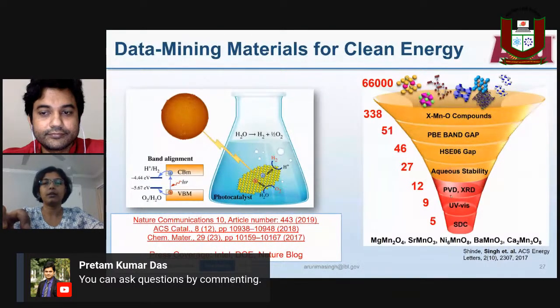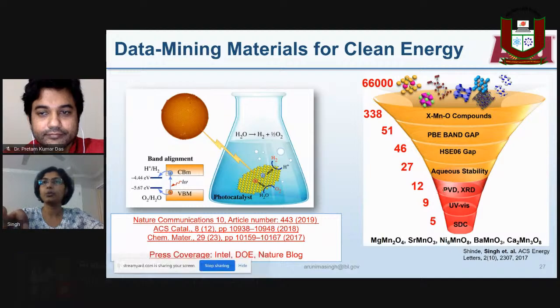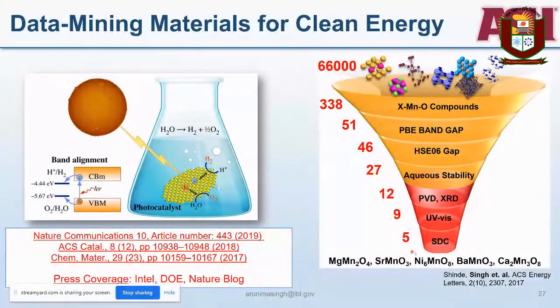And they were able to do growth of these candidates, characterize their structure using XRD, and then they were able to do all of these studies in a high throughput manner. They looked at their band gaps using UV-vis spectroscopy, and then they used scanning droplet cells to do a high throughput study of whether these candidates were actually converting water to hydrogen gas and oxygen gas. And indeed, we found these 5 new candidates which have never been studied for water splitting. And there are many other such success stories which I'm not going to be talking about today. But you can see that computations can play an enormous role in identifying new materials or materials for a specific application.